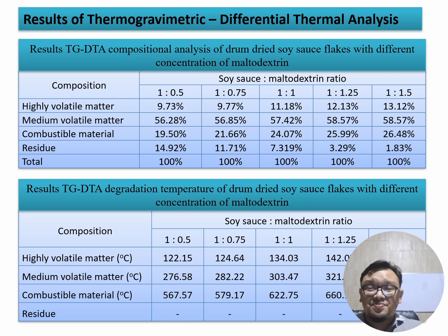So we see that once our soy sauce is encapsulated, the maltodextrin encapsulates the volatiles, the taste and smell of our soy sauce, which is seen in the table in the highly volatile matter, medium volatile matter, and combustible matter. We see that this composition increases as the composition of maltodextrin also increases. We see the opposite in the residual. The residue is about salt and minerals present in our material. As you can see, as the maltodextrin increases, the residue decreases because of dilution, since the salt composition is reduced. Of course, it becomes less salty because the maltodextrin in our material increases.